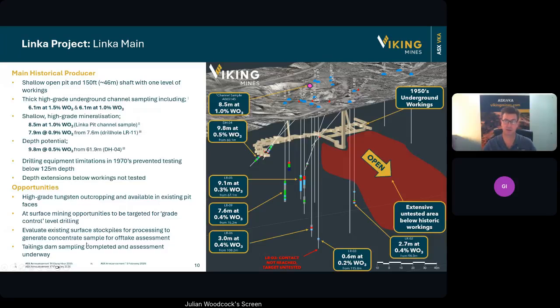What this means is we believe there's sufficient material in the stockpile and at a sufficient grade, which we're confirming with our current sampling, that we may be able to look to toll treat that once we've established the flow sheet and completed the metallurgical test work, which will allow us to generate several tons of scheelite concentrate, which we can then look to give to a variety of off-takers to assess and potentially lead into future agreements with them.